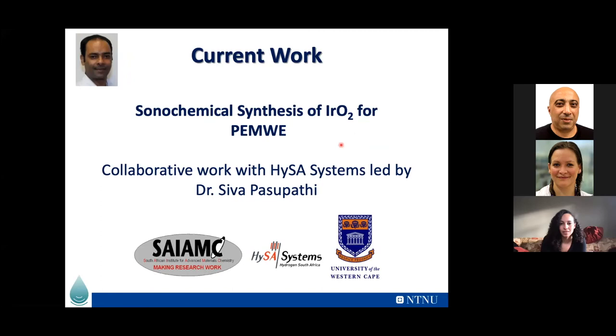This is also another work that I've been doing with Dr. Siva Pasupathi at the University of the Western Cape, where we're looking at the production of iridium oxide using ultrasound. We are using between 20 kilohertz and 1 megahertz to see where we can find a sweet spot here. We know that if we increase the frequency of ultrasound, you get more cavitation events, more sonolysis events, and more hydroxyl radicals and H radicals formation. So we want to know where we get maximum yield, but also sizes which are attractive to PEM water electrolyzers and PEM fuel cells, for instance.